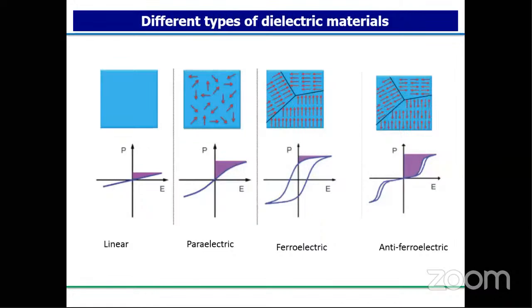However, as I told you previously, what is my requirement? I need to have large breakdown strength, that means large E, and the difference delta P should be as high as possible. Here, the conventional ferroelectrics have a nearly square hysteresis loop. That means PR and PS are almost the same. Otherwise, I can say the difference between P max and PR is very small. There, they have the disadvantage. From that expression, what we understand is, to have high energy storage in a capacitor, we need large E as well as large delta P. Because of the squareness of the hysteresis in ferroelectric materials, delta P is very small. So now I need to improve that delta P.